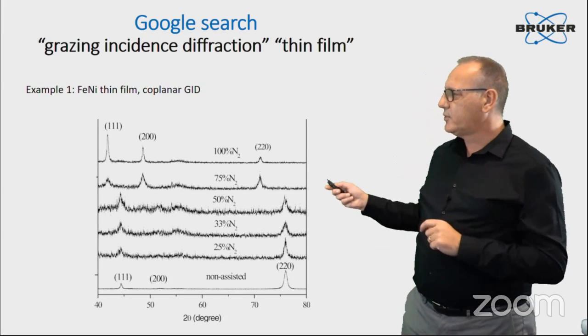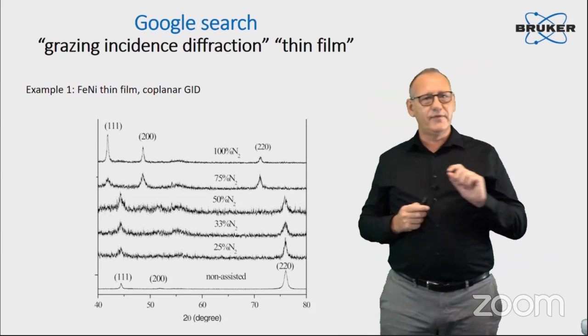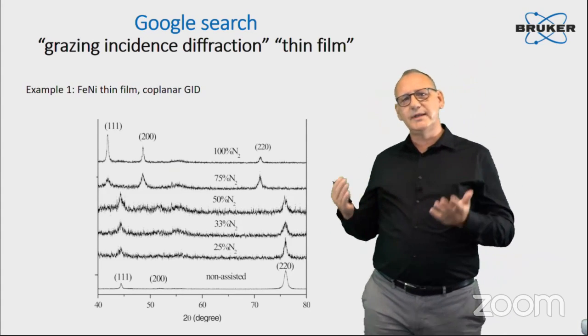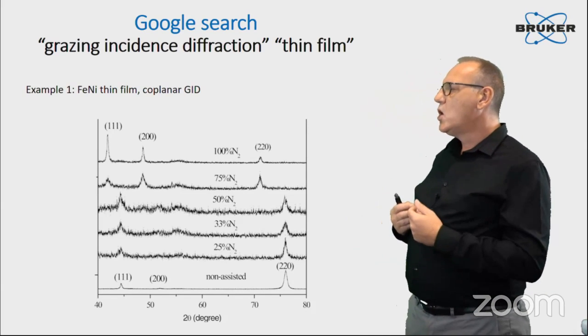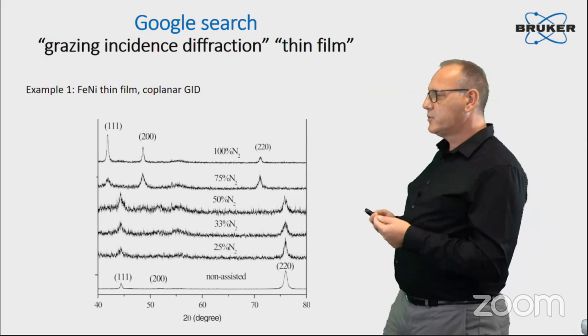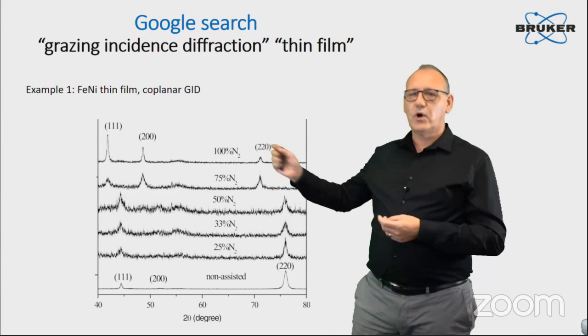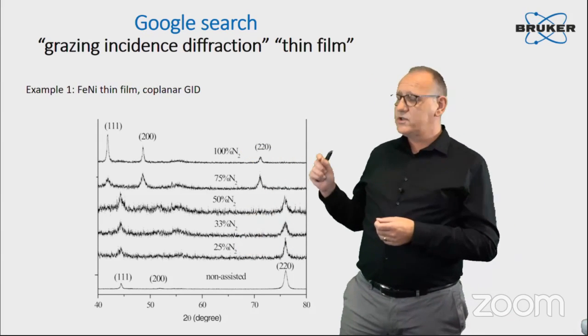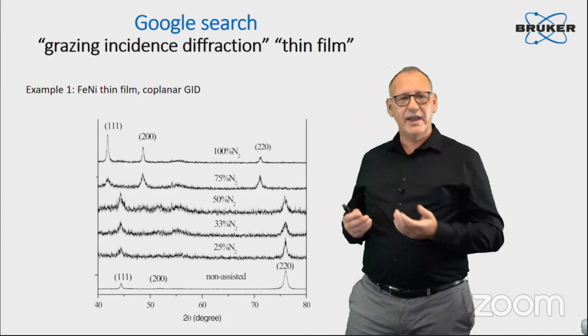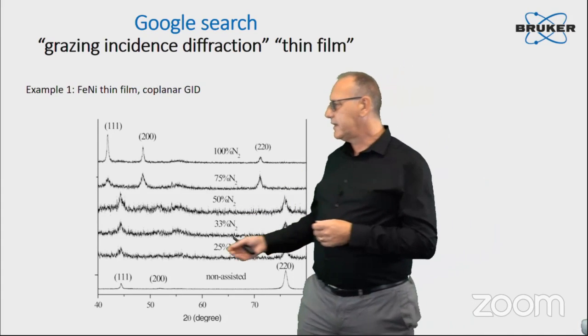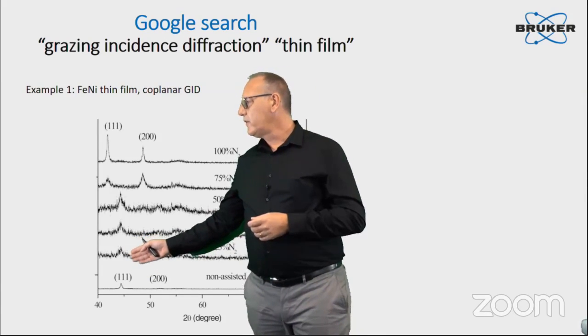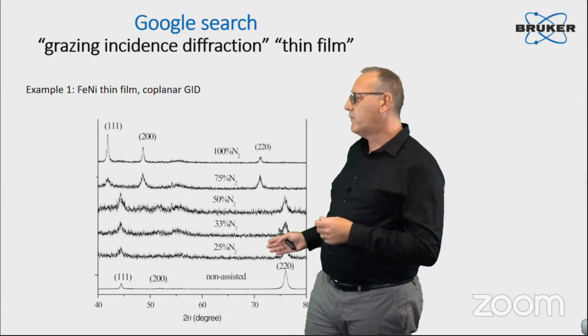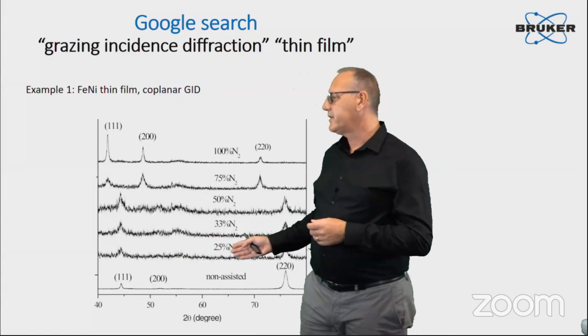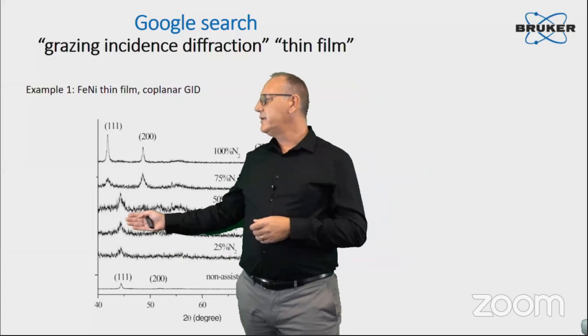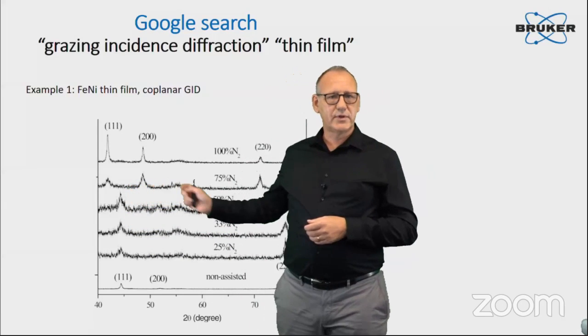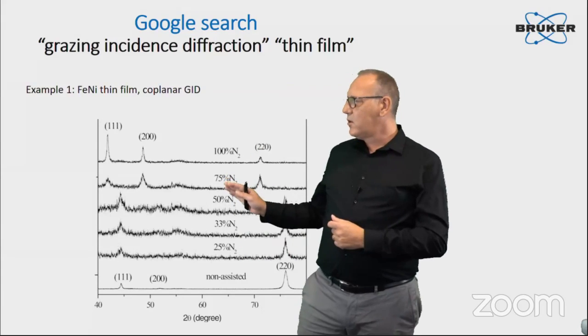So in this first example, this is an iron nickel thin film, and the people exposed this thin film, probably during the growth, to different nitrogen atmospheres, from 25% up to 100%. The goal of this GID measurement is to observe changes in the material. So we see that first we start with a phase. These are the 111, 200, and 220 peaks of the initial phase, at 25% nitrogen. And if you increase the content, you see that at some point, you have a phase transition. So this is the goal of this measurement.